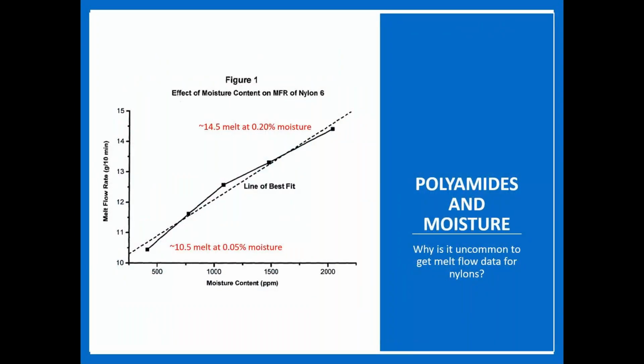So, speaking about moisture absorption specifically, I wanted to address something that we get asked for kind of often, and that is, can I get melt flow data for my polyamides? The reason we typically do not provide that is because the material itself is so affected by moisture that it starts to affect the data that you're going to receive. In this graph you can see it's the same material at different moisture contents, and you get different melt values at the different moisture contents. It's going to have the exact same viscosity if you tested it another way. But if I do a melt flow test, MFR, and I'm down at 0.05% moisture, which is kind of where we want you to be when you go to run it, you're at about a 10.5 melt.